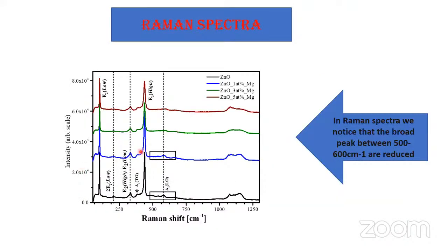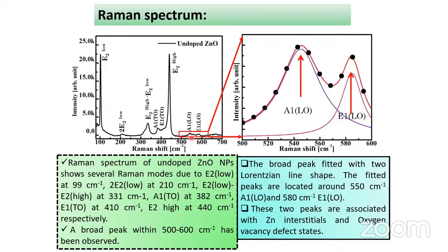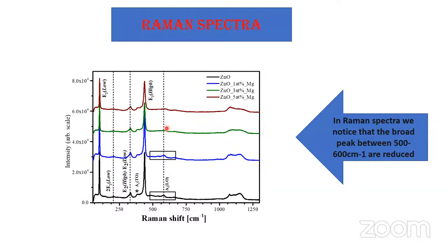This is the Raman spectra of ZnO nanoparticle. We notice the defect peak, or broad peak, in between 500 to 600 centimeter inverse, and the broad peak decreases with increasing Mg concentration. Here we analyze this broad peak. The first peak, the A1 peak, is due to zinc interstitial vacancy, and the second peak is for oxygen vacancies. And we see that when the doping concentration increased, defects are not found.